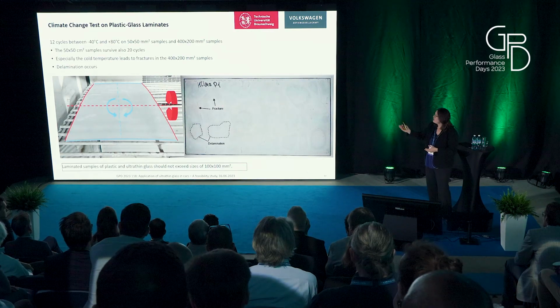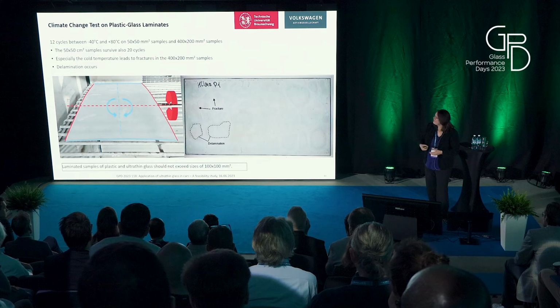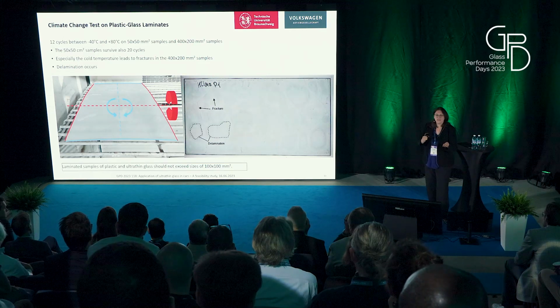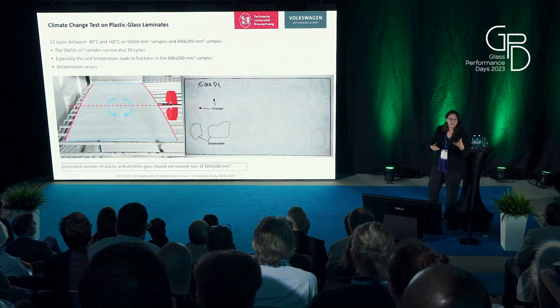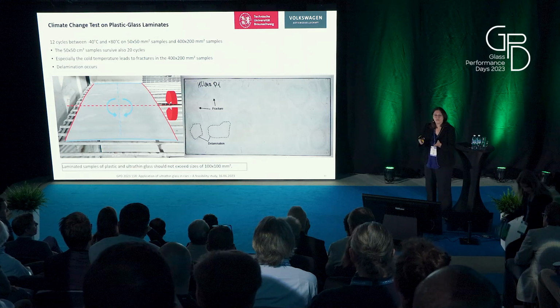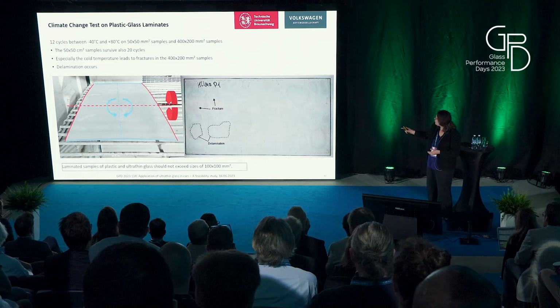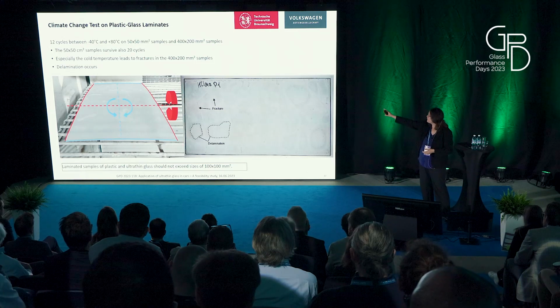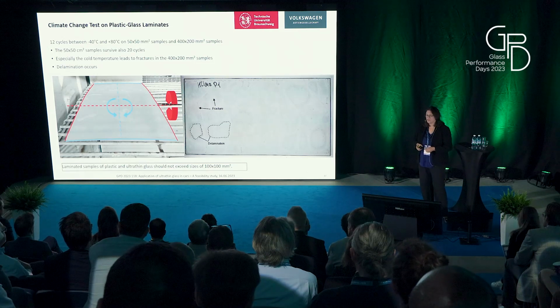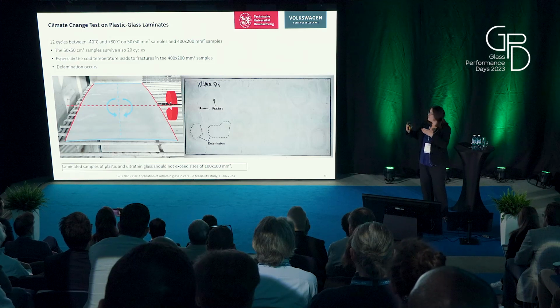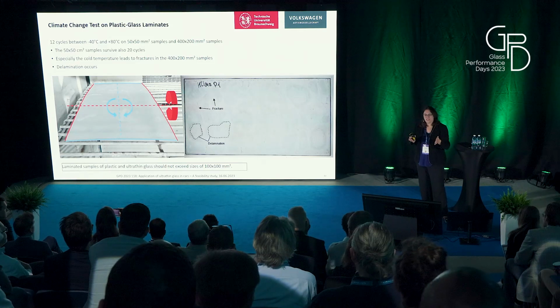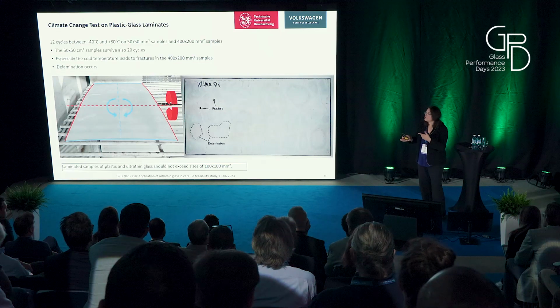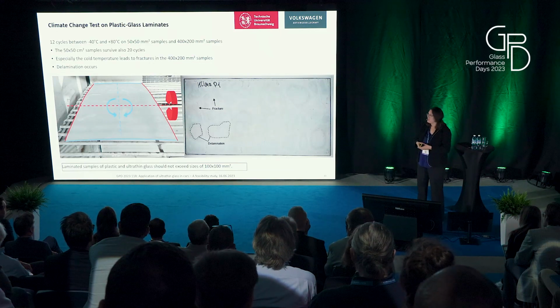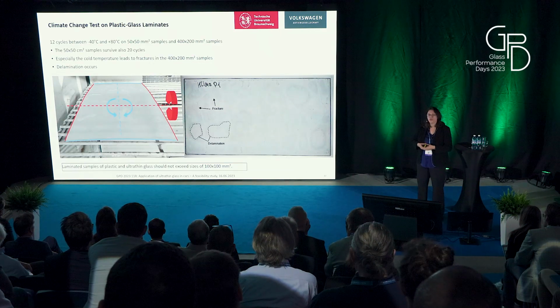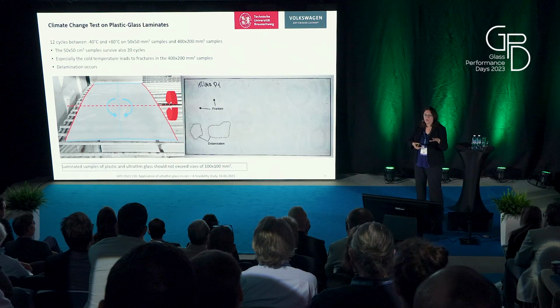And you see, especially at -40 degrees, that's the picture on the left side, there's a bending over two axes. And as we know, that's a problem for ultra-thin glass. So it's only flexible in one direction. And in the end, I hope you can see the contrast. You see a lot of cracks and also delamination after these tests. So unfortunately, the sample size, 40 by 20 centimeters, was too big for the combination of polycarbonate and glass. So what you could do is, if you go for that hybrid lamination, make smaller samples, or just laminate glass